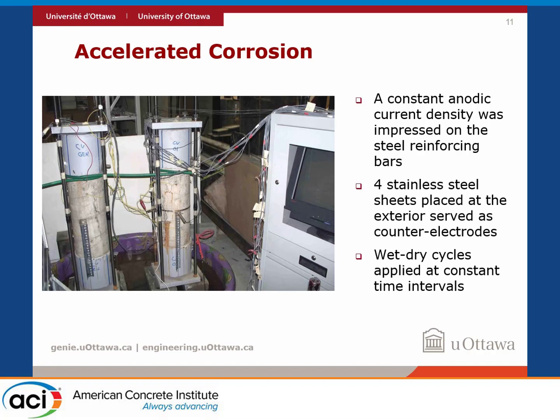To act as counter electrode, there were four per each column at each opposite side of perpendicular diameters. And instead of submerging the elements in water or in a sodium chloride solution, what we did was wrap the specimens with a perforated hose, and we would apply a wet and dry cycle at frequent intervals.